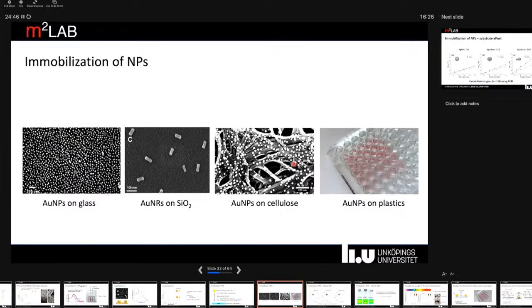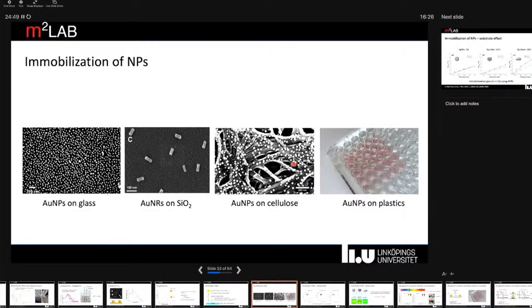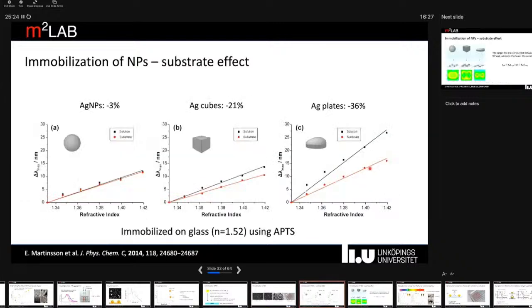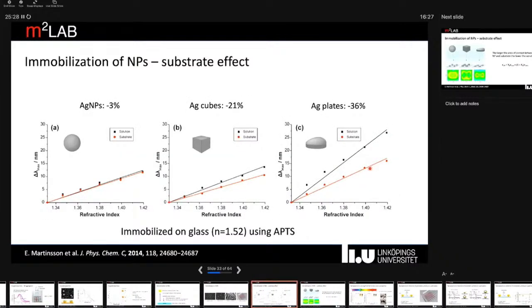And these are some examples of sensor surfaces that we've been working with, primarily quite a lot with gold particles on glass. And so this is what it can look like in electron microscope, or gold nanorods on plasma treated silicon oxide, or gold nanoparticles adsorbed to a nanocellulose substrate, or gold particles immobilized on a plastic substrate. So there are many options here. So depending on your applications or what you want to study, you can essentially pick and choose whatever substrate works for you. But there are some things you need to take into account, also when choosing the substrate-particle combination.